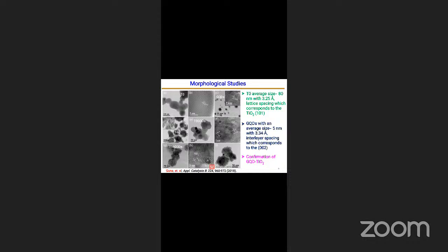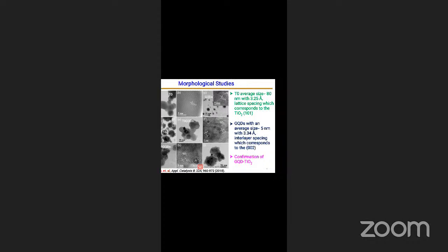Okay, next figure D is showing the T16 ball milled sample, and figure E is showing the T0 GQD sample with the TEM image, and figure F is showing the high resolution TEM image of the GQD and TiO2 sample, which comes from the formation of the GQD and TiO2 hybrid structure. And G is also showing the T16 GQDs with some black spots, which is the TiO2 coated on the graphene quantum dots, and the corresponding high resolution TEM image is shown in H. And I is the TEM image taken after photocatalysis, which is also showing the confirmation of GQD TiO2.